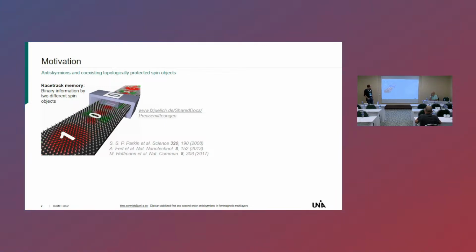Doesn't matter really much. But the problem with that approach is that the distance between the skyrmions, which would act as a 0 or a 1, is very volatile to pinning and other thermal fluctuations. So it would be a better approach to use different spin textures, like, for example, in this animation, an anti-skyrmion as a 0, to get this distance between the individual particles right. But for that, you would need a material that can host both skyrmions and anti-skyrmions under the same conditions.